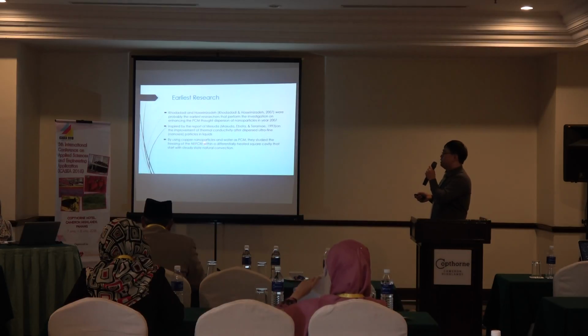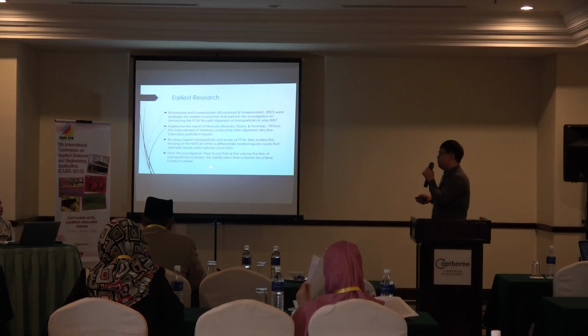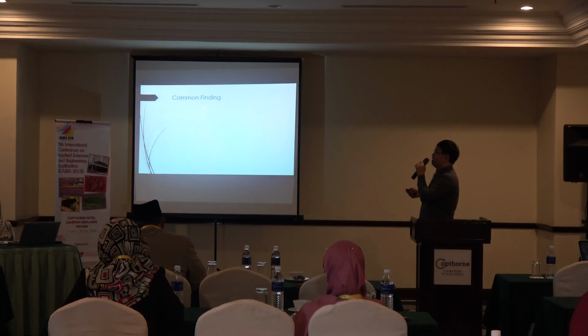So by using copper nanoparticles and water as PCM, they studied the freezing of the nano-enhanced PCM within a differentially heated square cavity that started with steady state natural convection. From the investigation, they found that as the volume fraction of the nanoparticles increased, the solidification time is shortened for a fixed Stefan number. After that, many researchers have been inspired to do similar studies.